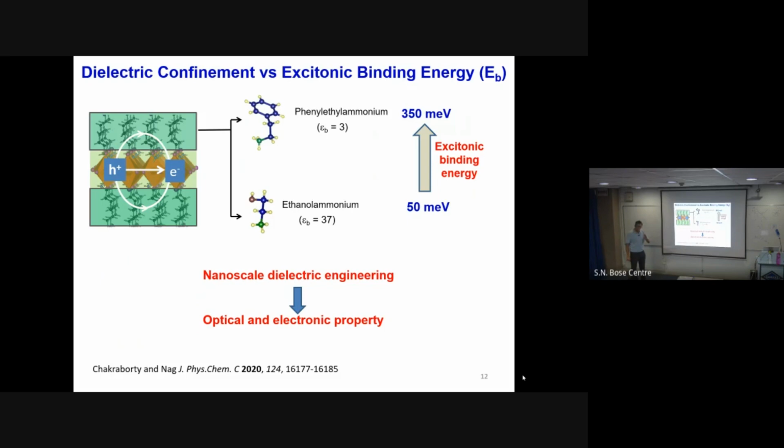less than 1 nanosecond. I'm talking about the fluorescence, photoluminescence lifetime, and in the other cases, you do a time-resolved photoluminescence measurement. You go to different temperatures, very low temperatures, but let's say for a given temperature, and then see what happens to the 50 meV number. The lifetimes will be kind of 7-8 times more. So in the lifetime data, you can see very clear signatures.